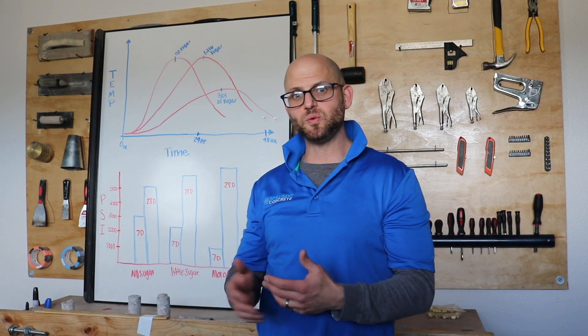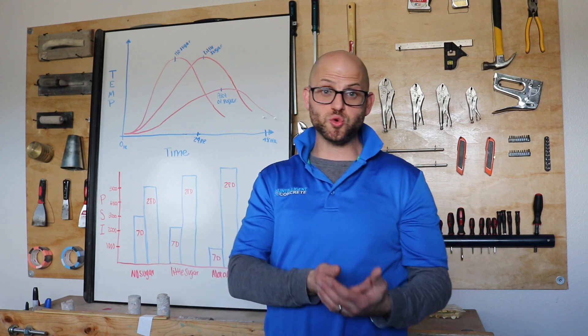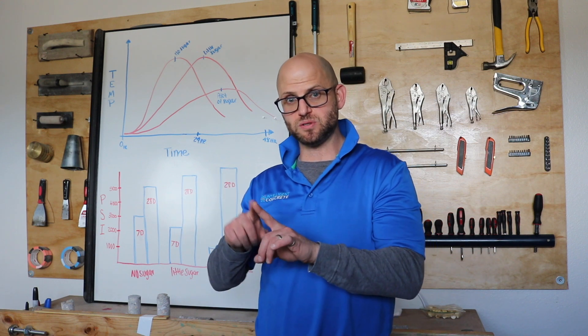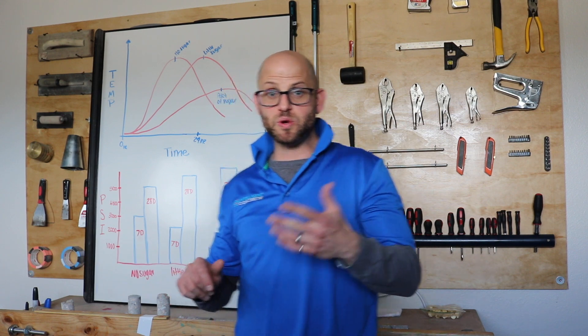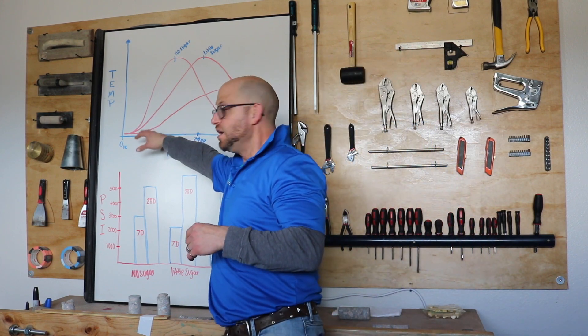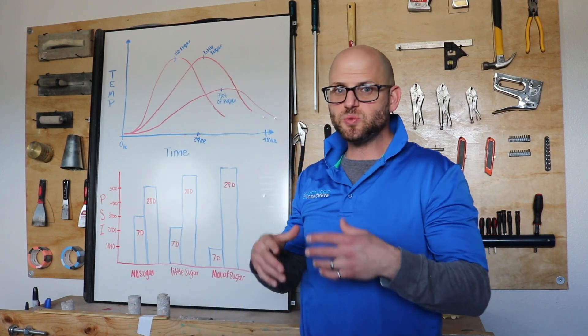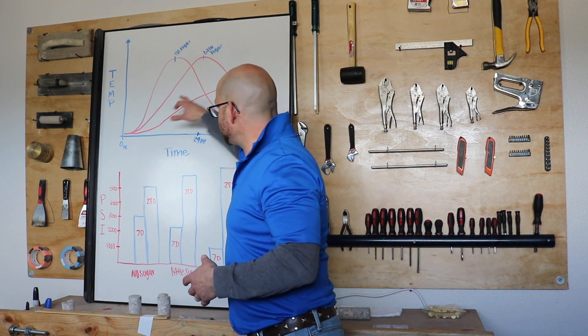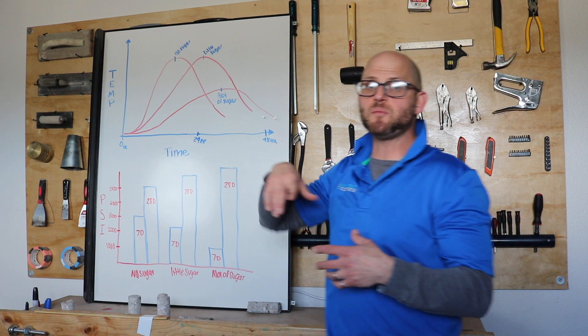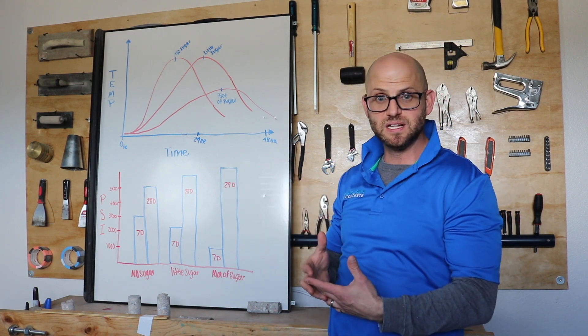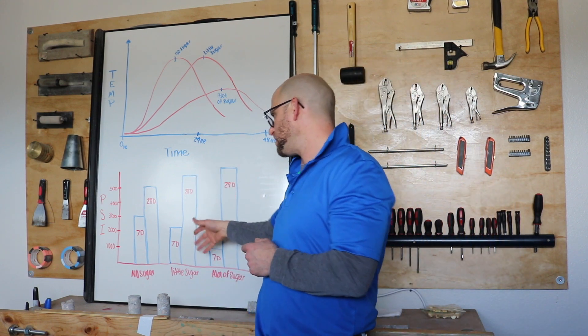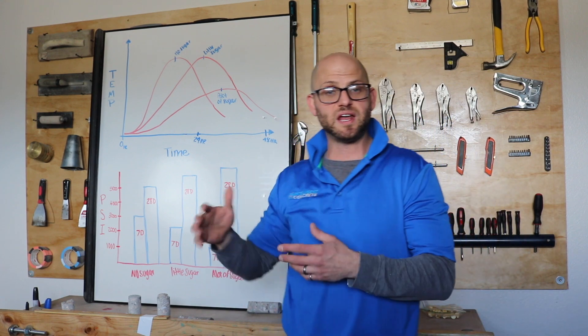The hypothesis, the guess, was that sugar would increase the set time — or reduce the degree of cement hydration over a longer period of time — meaning it would take longer to get to that same maturity. We would see that in two ways. If we had no sugar, our temperature over hydration over a 24-hour period would look like a pretty little bell curve right here. As we added more sugar, we'd see a lengthening of that curve, a drop in maximum temperature, and a huge reduction in our early strength at seven days.